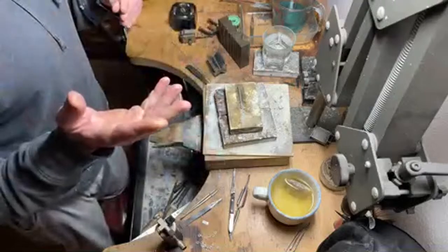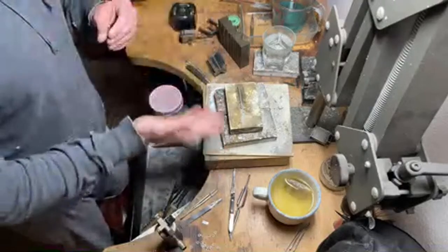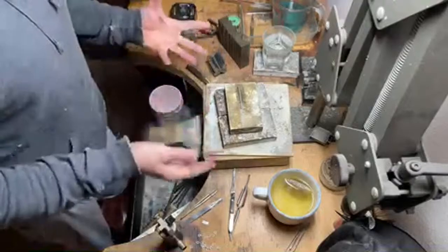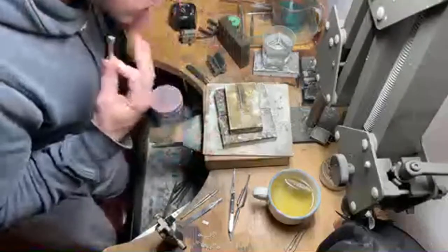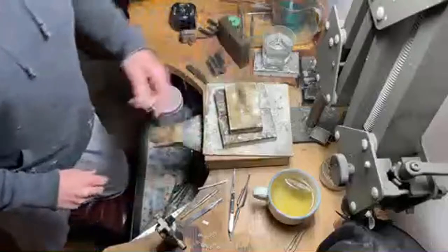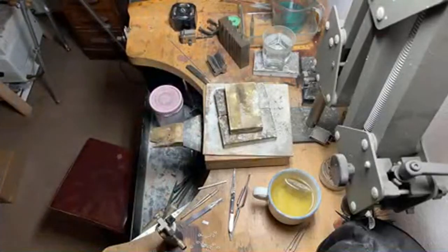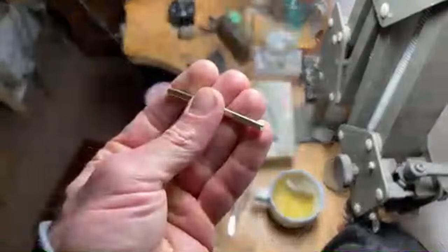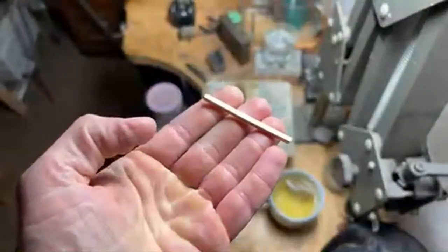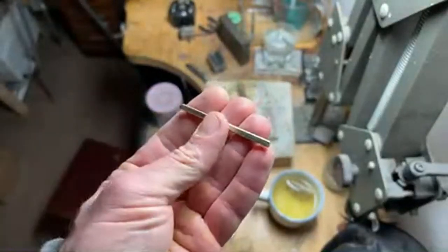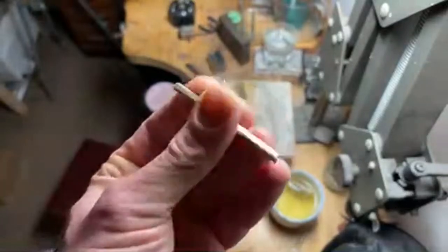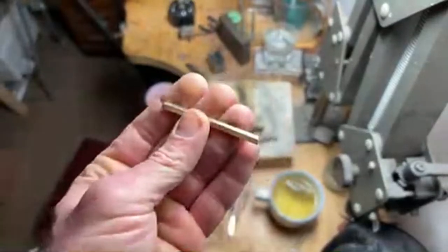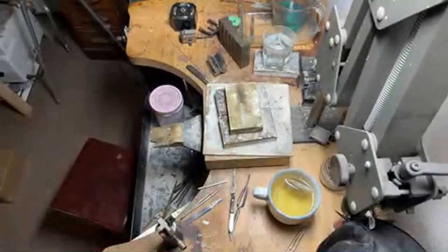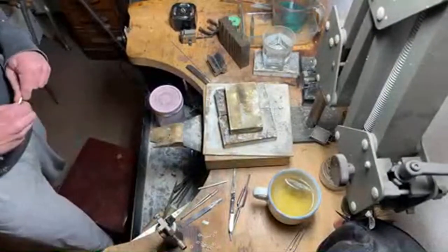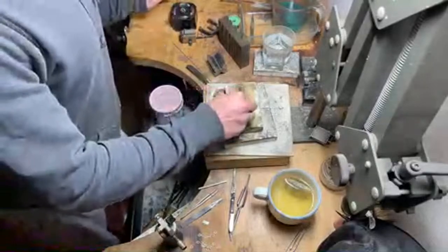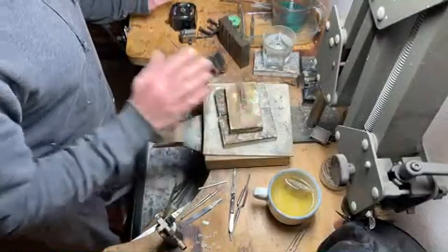I'll turn the lights off in here. I'll turn this bench light off so you can see the glow of the metal, and that's really how we gauge the temperature, is by the colour. As you can see, when they've been in the pickle, they're not bright yellow, they're kind of matte satin, quite light. They almost look somewhere between yellow gold and white gold when they're pickled like this, but yeah, it is yellow gold, but it will glow yellow. It will glow a dull red, and I'll hold it there for about a minute.